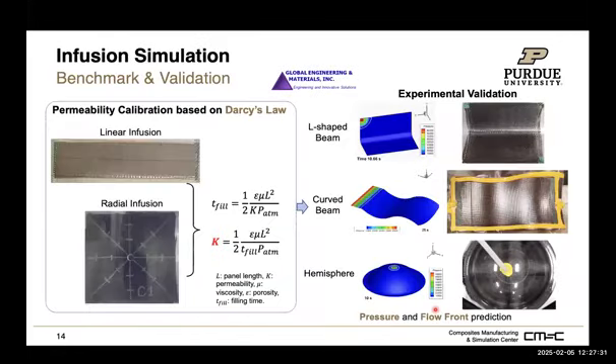Some of the very interesting work we have been doing all starts from validation. We still use a pretty engineering approach by homogenizing the entire infusion process based on Darcy's law. Basically we treat the preform as a porous medium and see how the flow passes through. On the experimental side, we need to run experiments to characterize the permeability of the fabric for our simulation work.